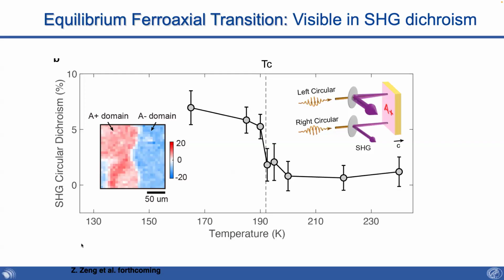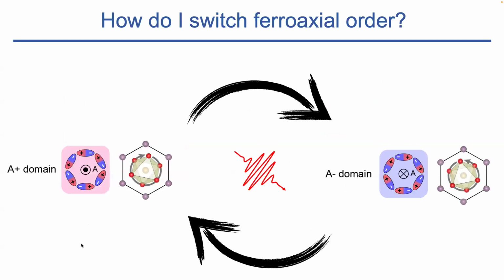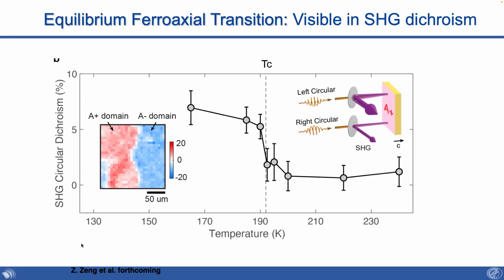Again, these don't couple at linear order to any field. The mode connected to this rotation is both non-IR active and silent in Raman. So it's difficult to see, but at higher order, you can measure this. And so in principle, you could probe it. Now you want to switch it. That's a very good question. I'm going to need something.